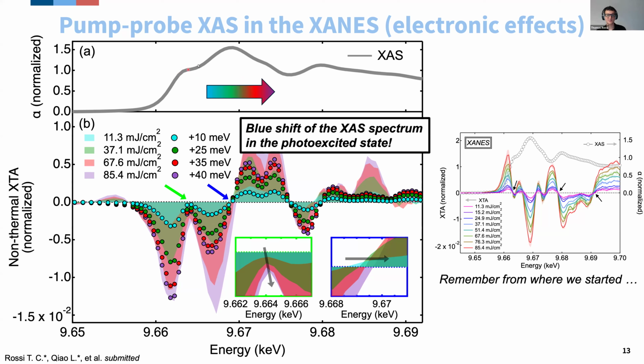And a qualitative way to show that is by actually doing the simulation. So I have taken this experimental XAS spectrum, shifted it to the right by different amounts, and this gives me the colored curves that you see here that qualitatively reproduce what is observed in the pump probe experiment. So we can conclude from this that there is a blue shift of the X-ray absorption spectrum in the photoexcited state. And in the next part, I will try to interpret where this blue shift comes from. But keep in mind from where we started, so this was our raw data that has both lattice heating and non-thermal contributions in it, and look at where we end up, to be able to tell that there is something non-thermal happening in the sample.